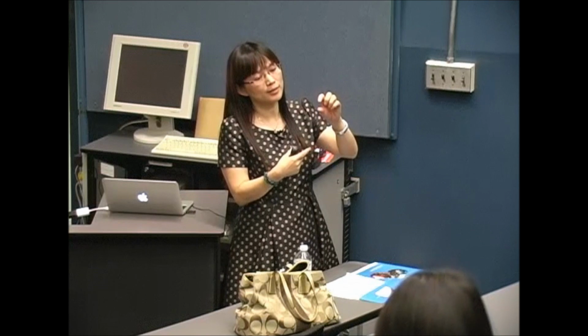That's because for RRAM, there are two different mechanisms. One is based on metal filament forming. For this kind of memory, one prerequisite is that the electrode is an active metal, like Cu. The basic mechanism is that this metal is easily oxidized, then migrates into the dielectric material. Then when an electric field is applied in the other direction, it can be reduced again, from ion to element.